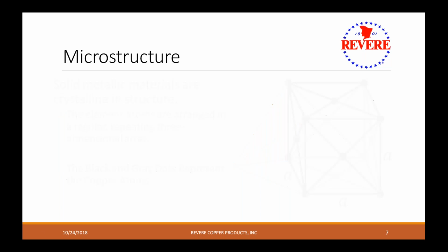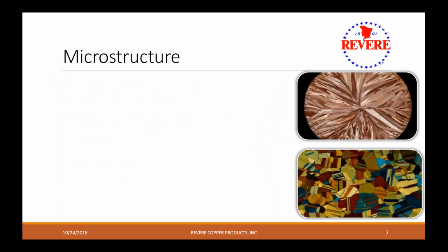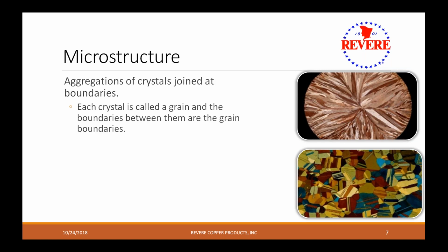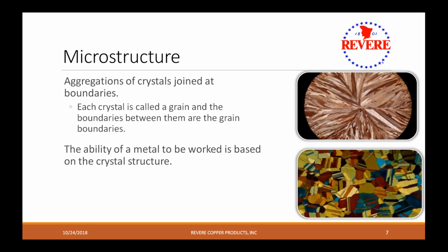If you look at copper under a microscope, you can see those crystals. Each of those crystals is called a grain, and the boundaries between them are grain boundaries. The top picture shows a billet that was cast, and it freezes toward the middle, and the grains grow toward that freeze point. So the grains are elongated towards the middle. The second picture more closely resembles copper that's been rolled or cold worked and annealed. In that case, the grains don't have directionality. The ability of metal to be worked is based on this crystalline structure, what you can do to it, what it's capable of.